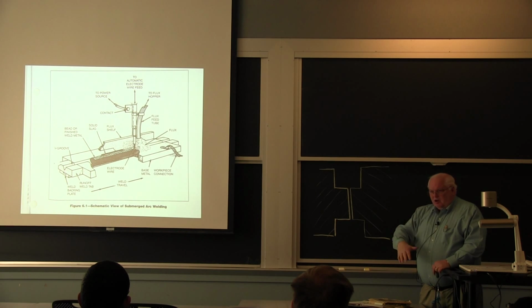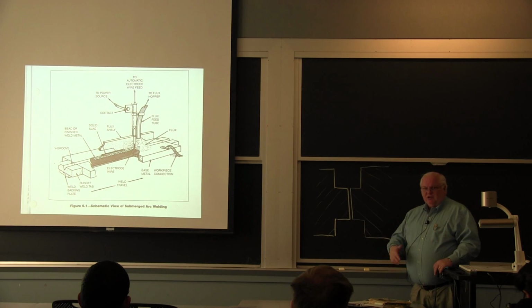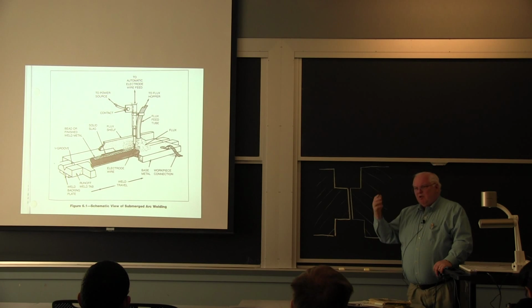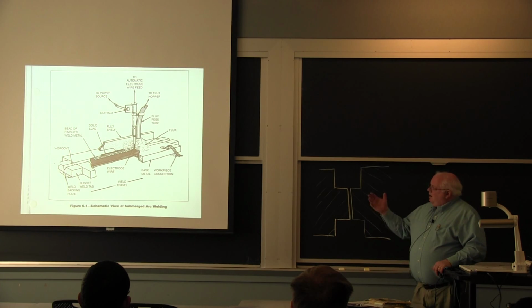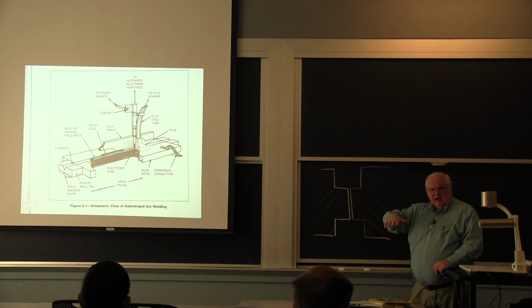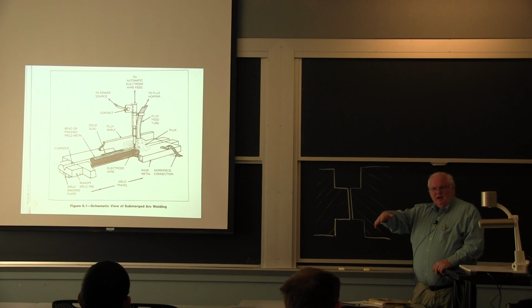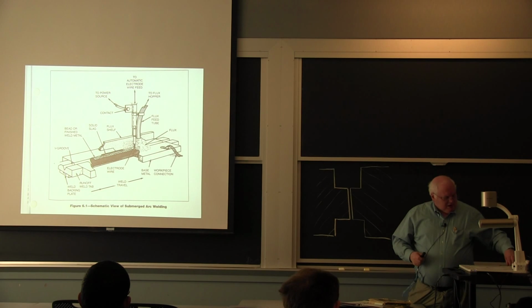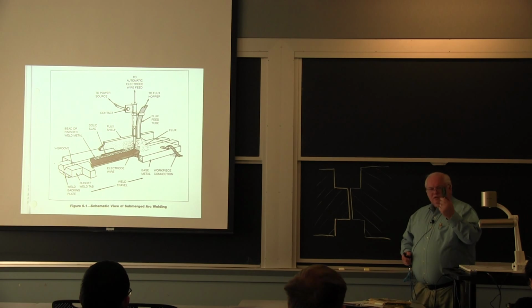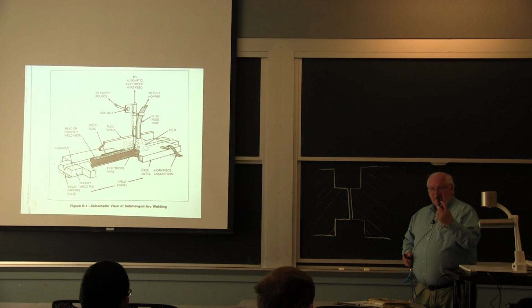So you have this arc that otherwise would be blowing sparks all over everywhere, it'd be too bright to see, but it's submerged beneath this sand, which melts and forms a glassy layer on top, which is the slag. Okay, so this is a submerged arc weld. My first research contract at MIT was on submerged arc welding of titanium.